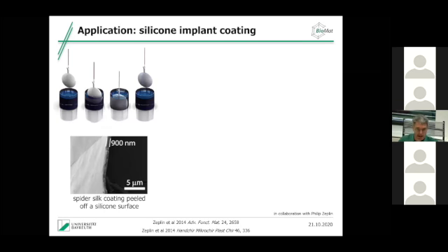And this was the very first setup many years ago. You see here the publication was in 2014. And now the product comes on the market, because these are silk-coated silicone breast implants. How to coat a silicone breast implant? It's quite easy. You just take this implant and dip it in a silk solution, an aqueous silk solution, I have to say. And silk molecules are amphiphilic, so they immediately assemble on the surface and make about a 1 micrometer thick film. So we get a shielding, a coating of this implant.